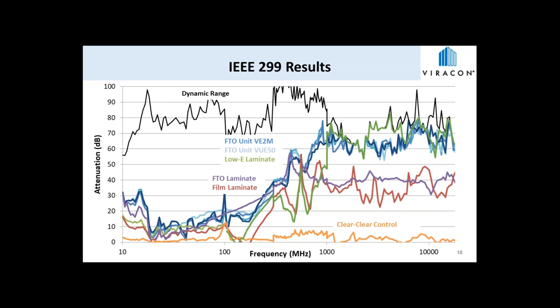However, the FTO laminate in purple does perform better than the film laminate up to about 800 megahertz, and then the film laminate catches up and performs similarly through 18 gigahertz. Focusing on the low E laminate in green and the FTO units in the different shades of blue, the FTO units again outperform the low E laminate until about 1 gigahertz, and then the low E laminate catches up and performs similarly throughout the rest of the test.